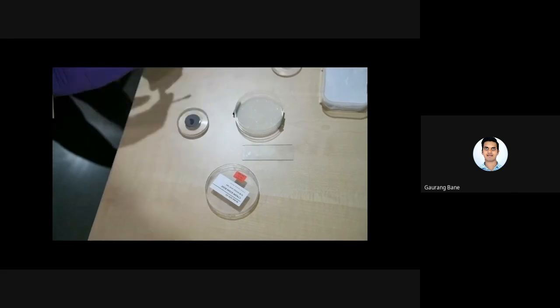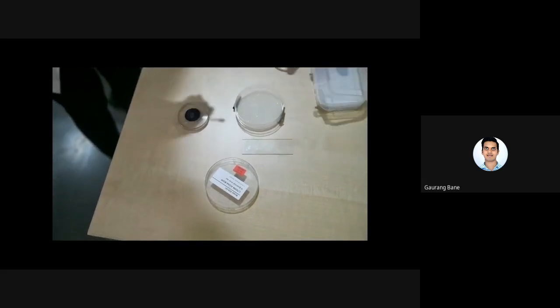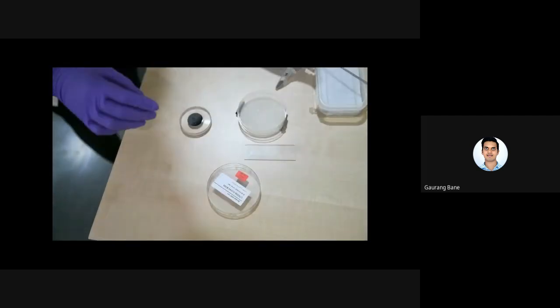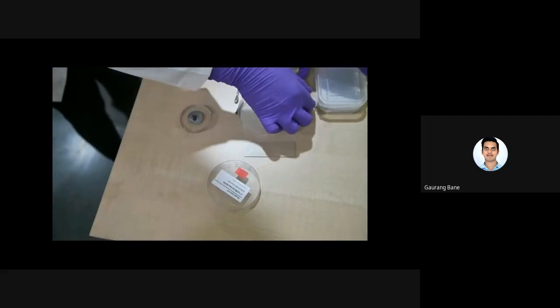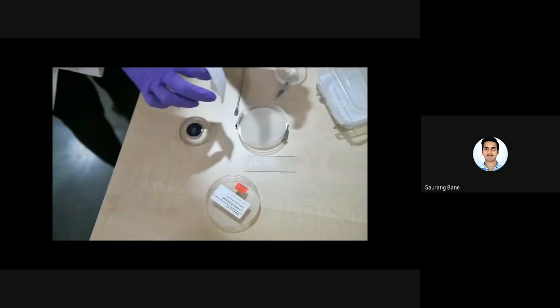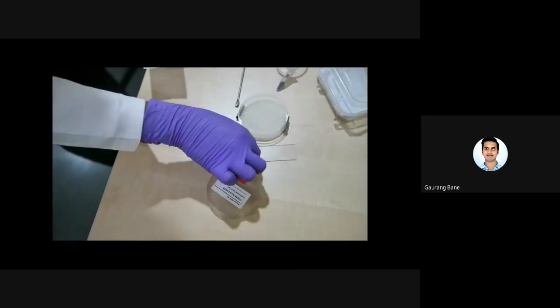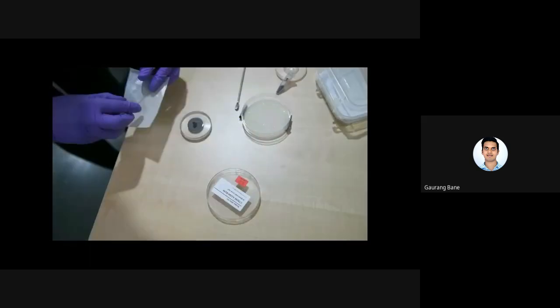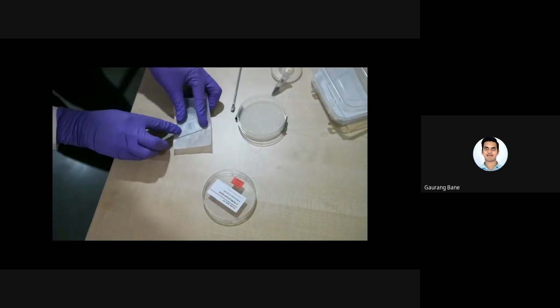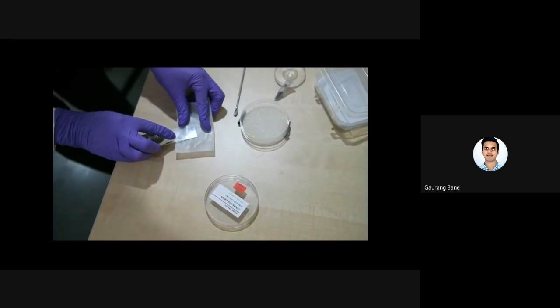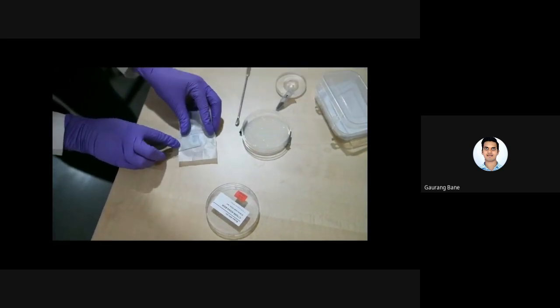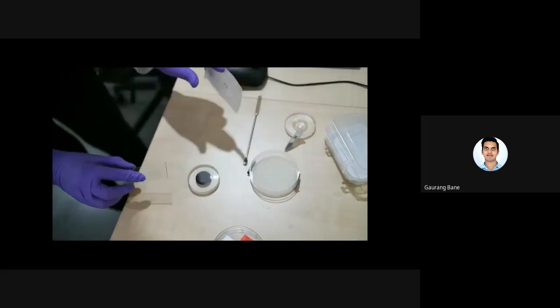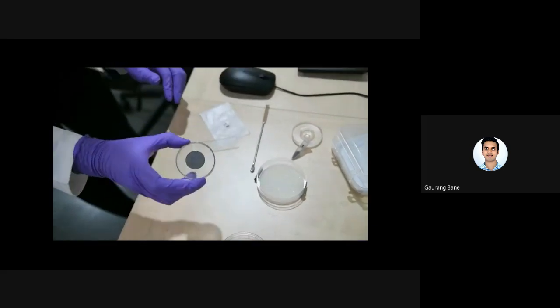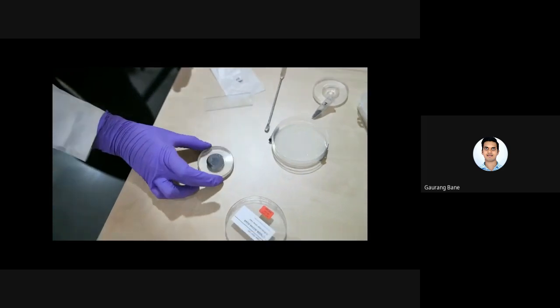When it comes to applications of XRD: identification of both crystalline and amorphous phases and determination of specimen purity, quantitative analysis of both crystalline and amorphous phases in multiphase mixtures, and microstructure analysis, where we can find out the crystallite size and microstrain in the sample. We can find out the bulk residual stress resulting from thermal treatment or machining in manufactured components. This is how we have to prepare the sample. It should be completely flat.